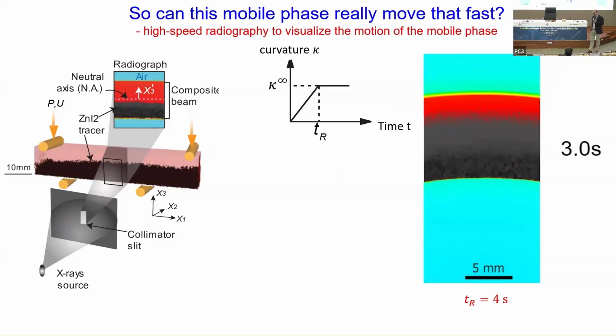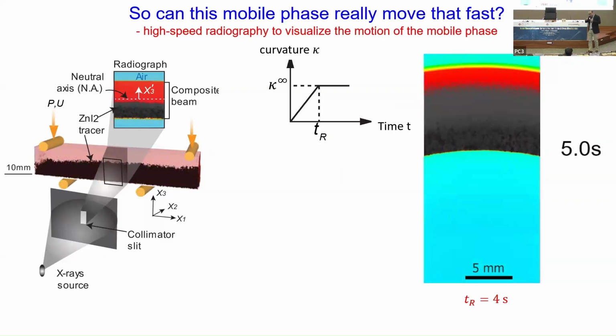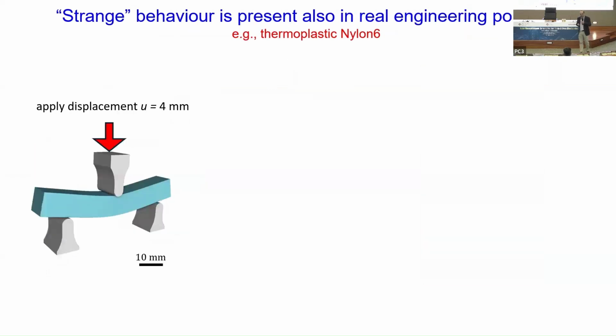And it's moving so fast that it is keeping up with the rate at which I'm deforming the specimen. And because it is keeping up with the rate at which I'm deforming the specimen, I am not observing any rate dependence in this problem. Because at every step, this is essentially remaining in equilibrium, because the diffusion is not occurring slowly. Now, what is the process by which this diffusion is occurring so fast? I don't know. But this is the new physics that was showing up.